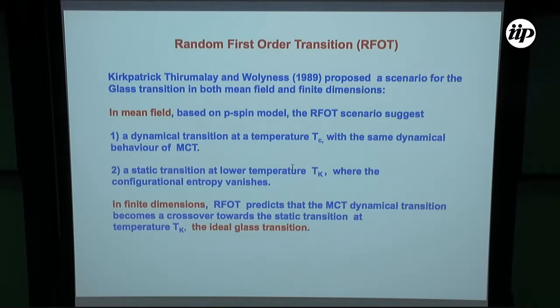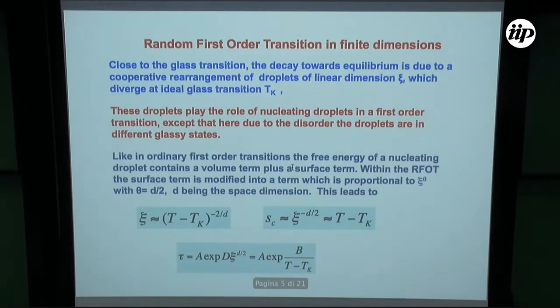In finite dimensions, random first-order transition is modified and predicts, in fact, that the mode coupling theory dynamical transition is smoothed and becomes just a crossover towards the static transition, which occurs at a lower temperature, TK. And this static transition is called the ideal glass transition. So one of the main ingredients of this random first-order transition in finite dimension is that close to the glass transition, the decay towards equilibrium is due to a cooperative rearrangement of a region, if you like, of droplets of linear dimension xi, and this xi diverges as you approach the ideal glass transition.